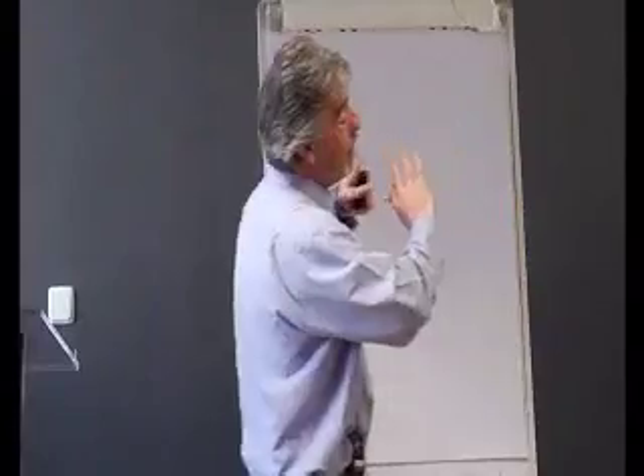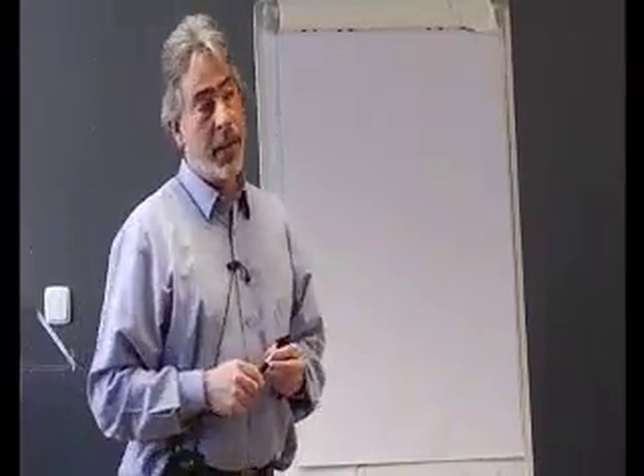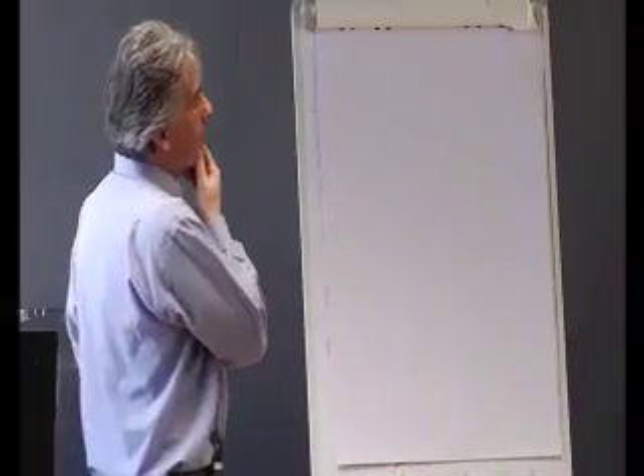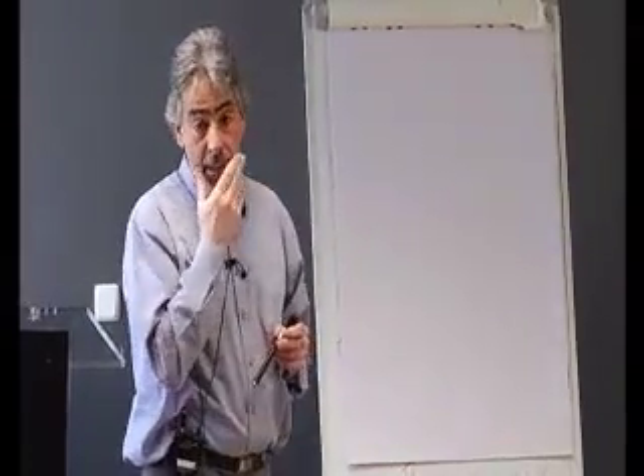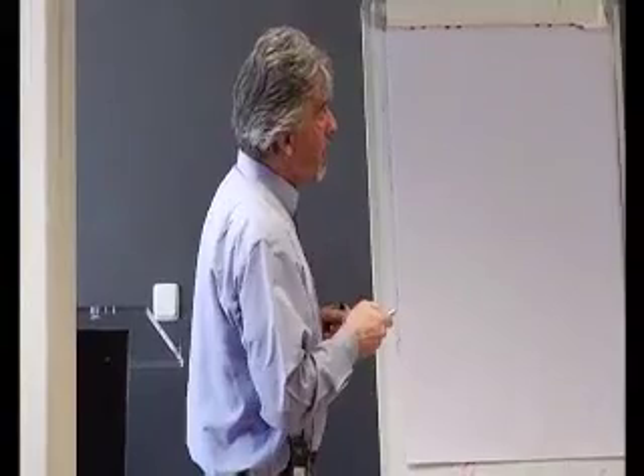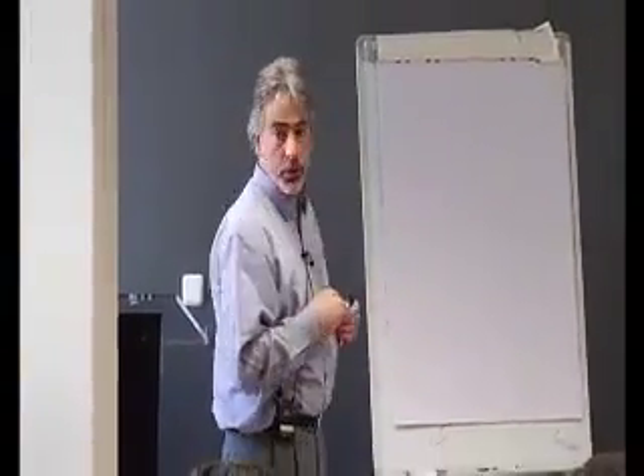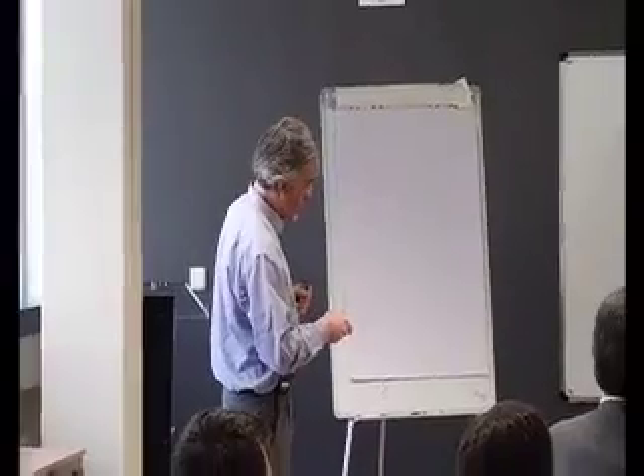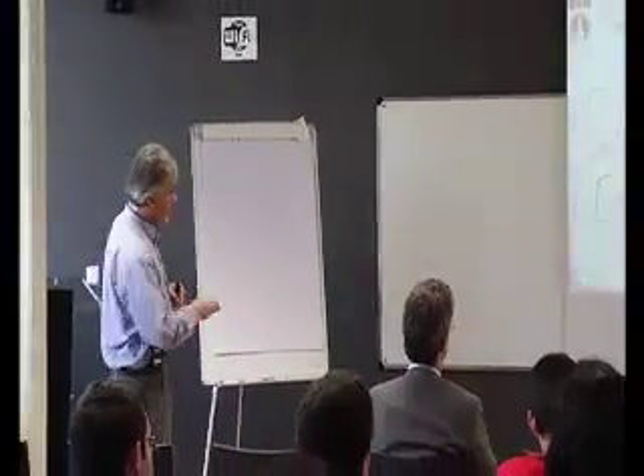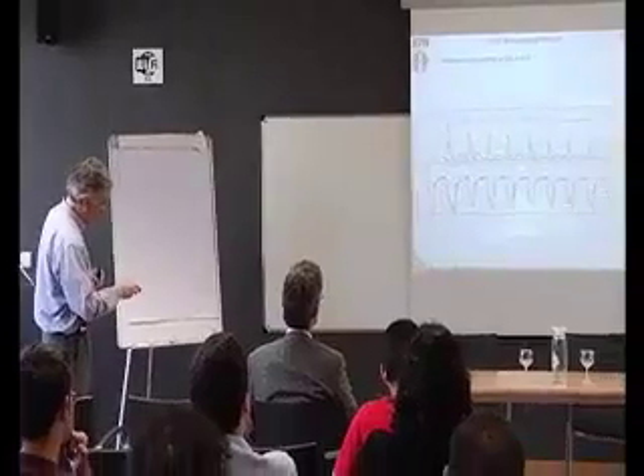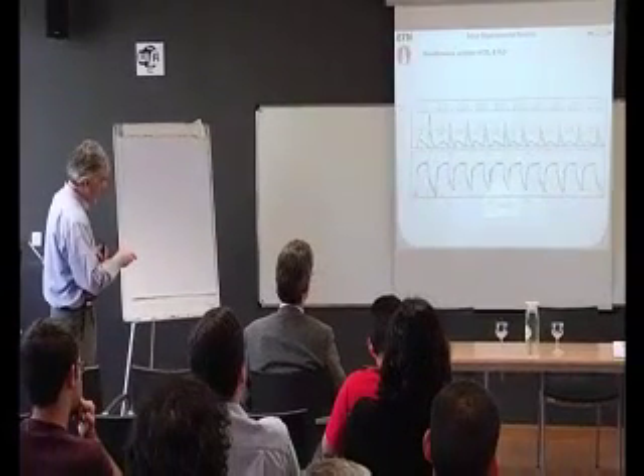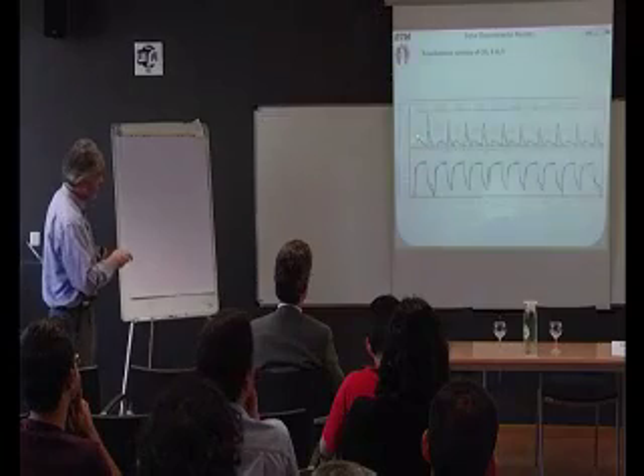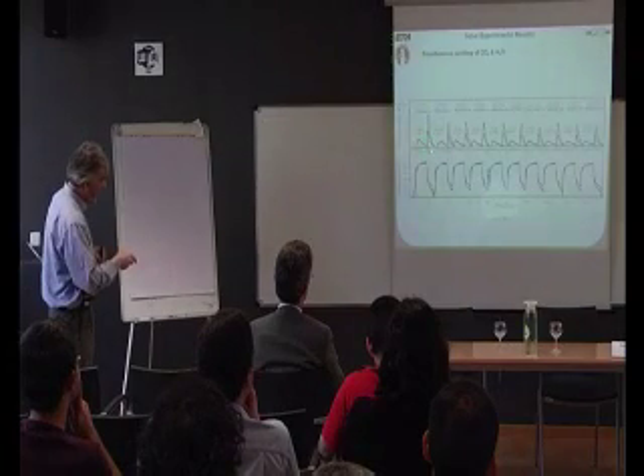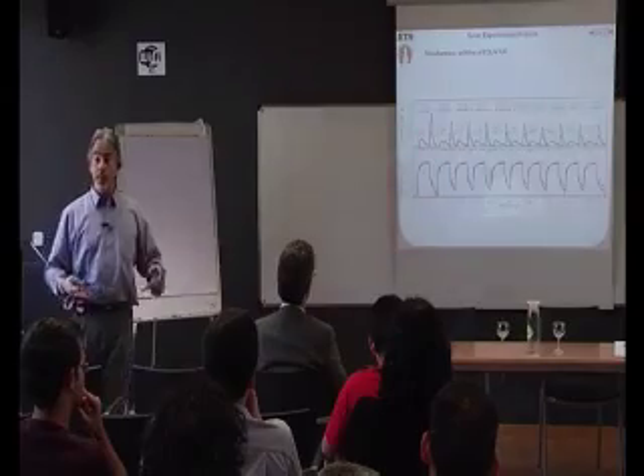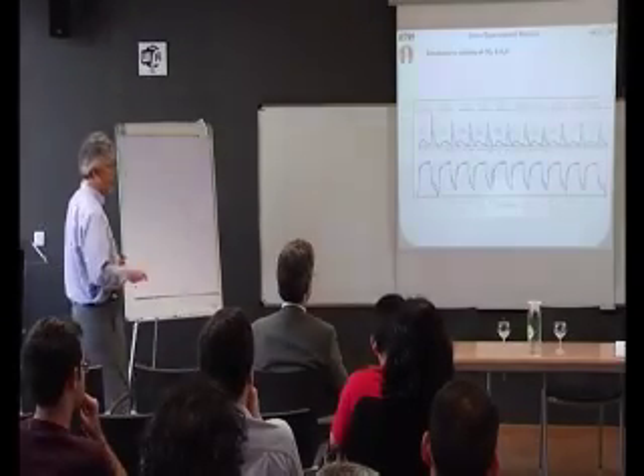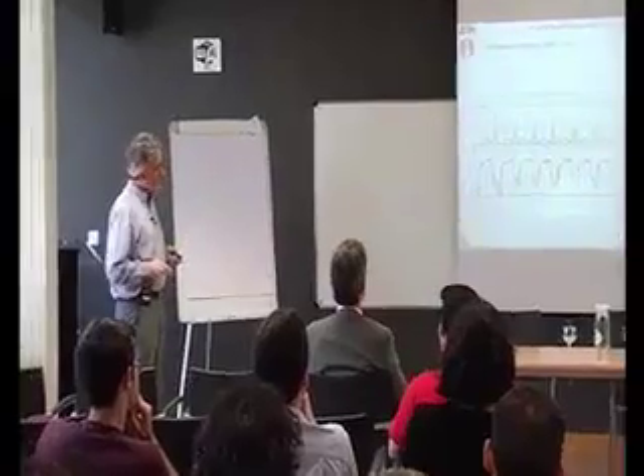And this is a very recent result. It was obtained in the lab about a week ago. We have here 10 consecutive cycles where we are simultaneously splitting CO2 and water. So here the lower curve is showing you the temperature in 2 locations. Again, reduction, oxidation. And here you see in red the oxygen peak of the 10 cycles, and in blue and green, this is the solar syngas production, 10 consecutive cycles.